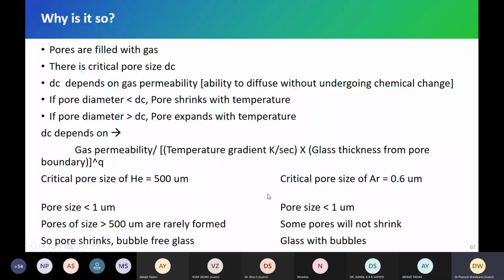Sorry for the disruption. All right, what I want to convey is that we don't need to go into much detail of the helium or argon. We generally use helium and argon gas to remove these bubbles. So that optimum ratio of helium and argon is very important. The reason is that the critical pore size of helium is 500 micron, while argon is much lower than that, so there is a lot more possibility of having bubbles with argon gas than with helium. As you can see, the critical pore size of helium is 500 micron. The critical pore size of argon is 0.6 micron.